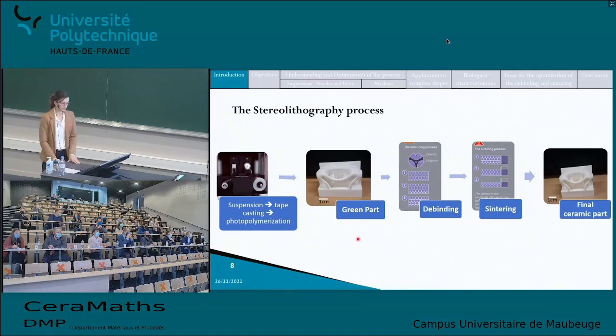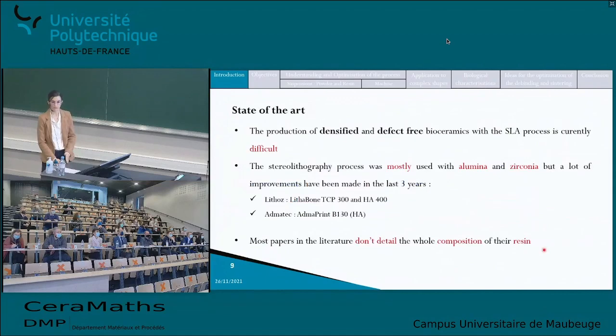At the moment, the production of densified and defect-free bioceramics with the SLA process is very difficult because a lot of defects and cracks can appear during the different steps of the process, especially during the printing, debinding and sintering steps. Moreover, the stereolithography process was mostly used with alumina and zirconia when I started this PhD, but there has been a lot of improvement in the last 3 years, and there are, for example, 2 companies now commercializing suspensions with TCP or hydroxyapatite material, Lithoz and Admatec.